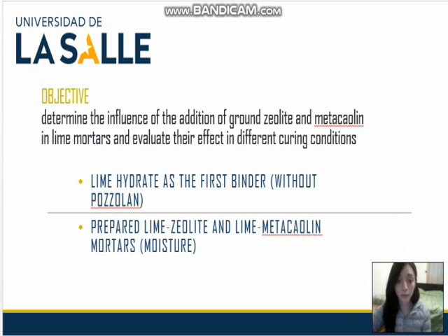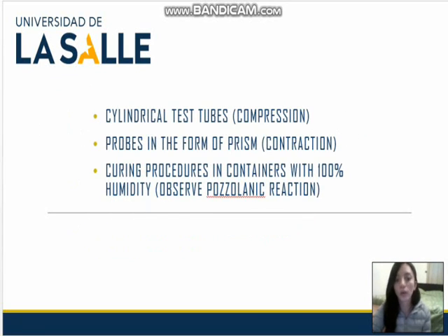The objective in this practice is to determine the influence of the addition of ground zeolite and metakaolin in lime mortars and evaluate their effect in different curing conditions. Lime hydrate was used as the binder, preparing lime-zeolite and lime-metakaolin mortars. Cylindrical test tubes were used for the compression tests, prism-shaped probes for the contractions, and curing procedures in containers with